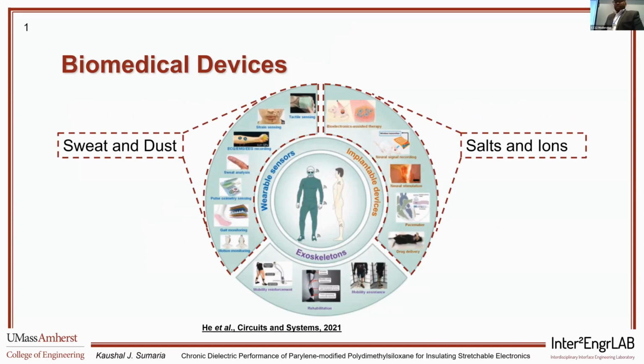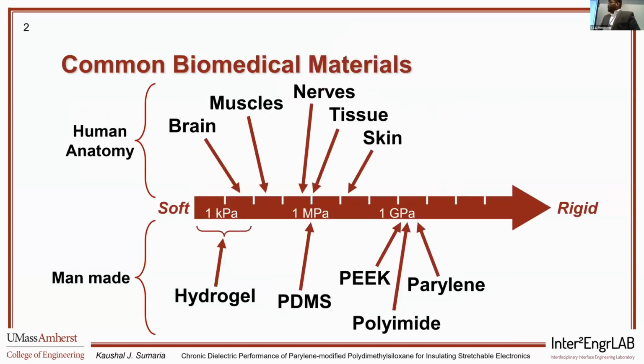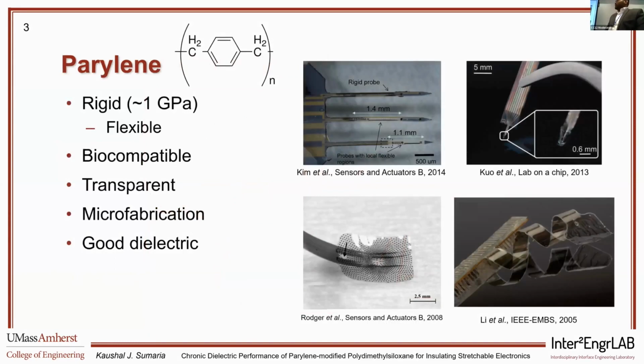So let's take a look at the biomedical materials commonly used. If you look at the human anatomy, most of the things are concentrated around or less than 10 megapascal. However, the materials used for these sensors are either very stiff in the 1 gigapascal range, or something softer like PDMS, or something even softer like hydrogel. However, the PDMS and parylene are really useful because there are very mature techniques for fabrication of these materials. So let's take a look more closely at these two materials.